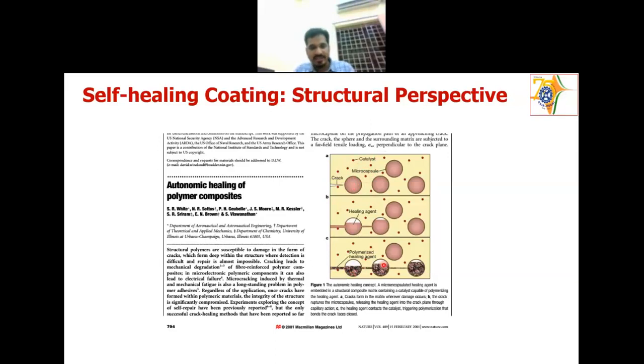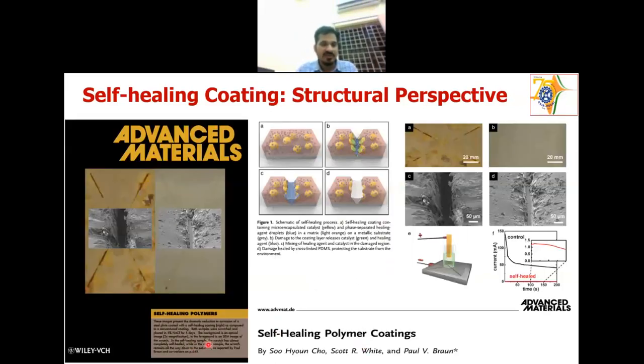The same group later developed their work further, and I can show you this article, which came as a cover page in Advanced Materials in 2009. And you can see this is a coating. They made a scratch here. This is an image of the scratch. And when the healing happens, you can see the depth decreased, not complete recovery, but something recovered here. And electrochemically also they proved that. You can see this is the current we are getting in the control sample, but when it is healed, the current is less here. This is the mechanism. When you make some defect, the capsules rupture and the healing agent comes out and it self-heals.